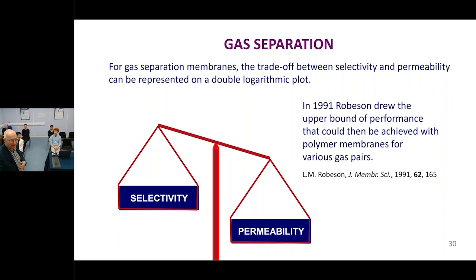And permeability, incidentally, I said before, that's normalized for the pressure difference and the thickness. And you'll see some rather odd units which don't relate to anything else in the world. The Barrer unit, which people use. People from Imperial, especially. But what Robeson did, he just drew a line through the best performing polymers. And that sort of showed the boundary of what was possible at that point in time. And the question then has been, can one improve on that?